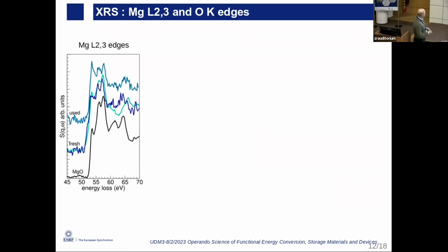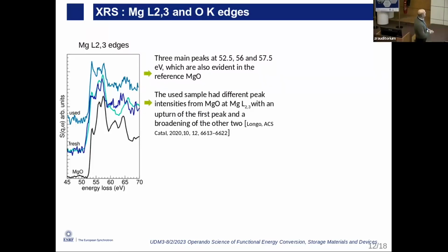So then, to fully conclude about the magnesium coordination, we went to study the low Z elements by doing the X-ray Raman spectroscopy. And so this is the Mg L23 edges, actually. And we do see, with respect to the MgO as a reference, that there are differences. The difference is that the ratio of the peaks is changing. In the fresh it is already changed, but in the used it's completely different, it's higher.